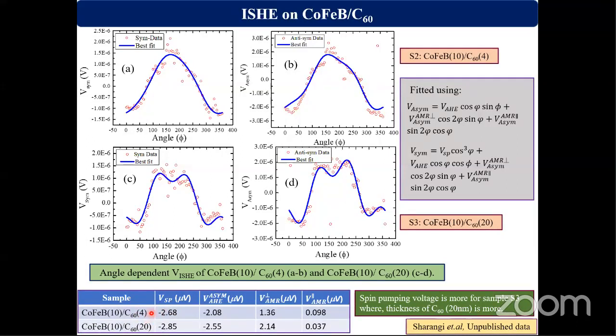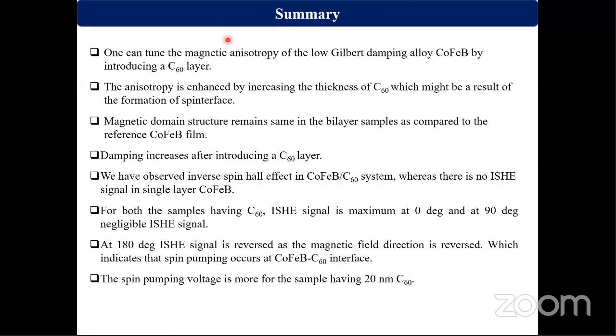So it has been observed that the spin pumping voltage is more for the sample 3, where the C60 thickness is also more. So in summary, we can tell that one can tune the magnetic anisotropy of this cobalt iron boron system by introducing a C60 layer, whereas there is no change in the domain structure. Also, by introducing a C60 layer, the damping also increases, and we have observed the inverse spin Hall effect in the cobalt iron boron C60 system, whereas there is no ISHE signal in the single layer cobalt iron boron. And the spin pumping voltage is more when the C60 thickness is more.